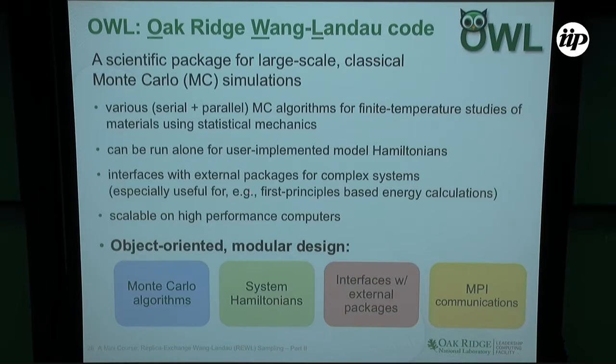The special thing about this is that we interface the Monte Carlo algorithms with external packages. For example, we have interfaced this with a lot of density functional theory codes. The motivation is that we want to study first principles Monte Carlo simulations, as opposed to molecular dynamics, where there is already ab initio molecular dynamics that calculates the forces from density functional theory, and then you do the molecular dynamics. And here we are actually simpler. We don't have to calculate the forces, we only need to calculate energies, and then we do ab initio Monte Carlo simulations.